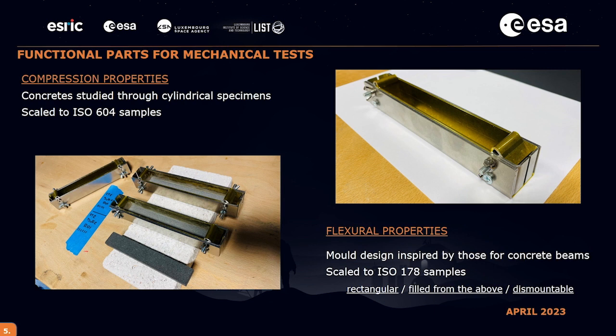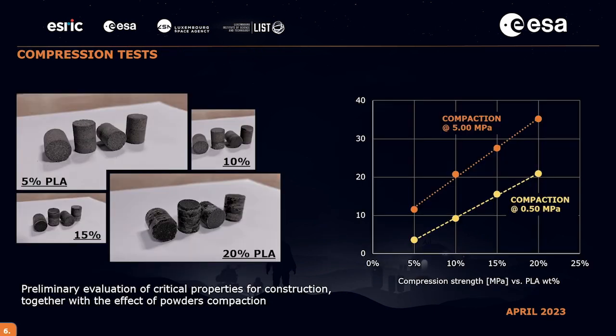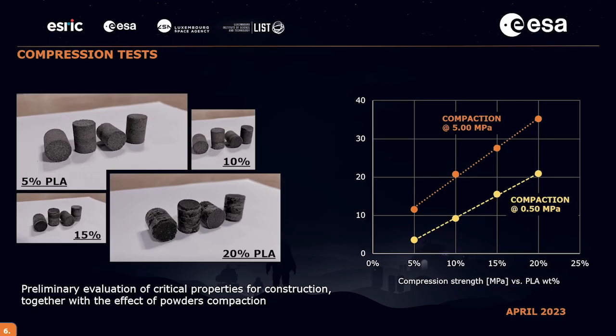So here I would like to follow on the pictures you see on the right, because that is the mold we use to manufacture the flexural specimens. You can see that it's rectangular, it can be filled from above, it is dismountable, and it has already an interesting dimension. It is 15 centimeters. So just picture in your mind that mold with another shape, maybe an interlockable one, and you have an idea of the target we would like to reach. Going back to the compression properties, with this slide, I would like to show you some of the preliminary results we got. The compression properties are really important when we talk about construction. And here we evaluate their behavior with respect to the amount of PLA, so the binder we put inside.